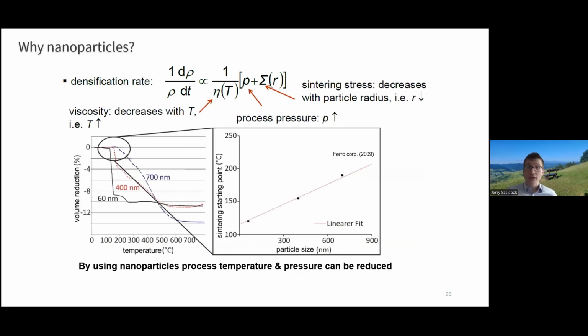Not only in my research, silver nanoparticles were used to reduce that. In our case, we developed nanoparticles during one of our projects. The particles are characterized by an average grain diameter of 6.5 nanometers, and they have quite a high content of organic shell to prevent grain agglomeration. The first joints we made using only silver nanoparticles as a functional phase were sintered at 300 degrees and 10 megapascals. Later, we reduced the pressure to 5 megapascals. The joints were characterized by shear stress resistance of about 10 megapascals, so comparable more to adhesives than to solders.